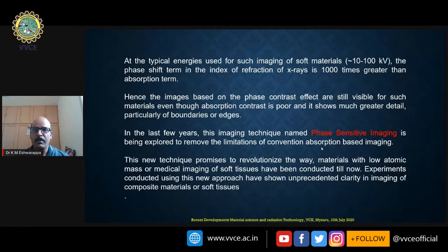For the same radiation, the change in the phase when it travels through a certain tissue or material is 1000 times more than the corresponding absorption term. Hence, this greater change in the phase gives very high contrast images with the neighboring tissues or materials. The images based on the phase contrast effect are still visible for such a material, even though absorption contrast is poor, and they show much greater detail, particularly of boundaries and edges. This imaging technique, named phase-sensitive imaging, is being explored to remove the limitations of conventional absorption-based imaging.